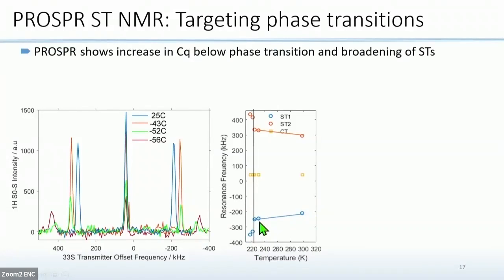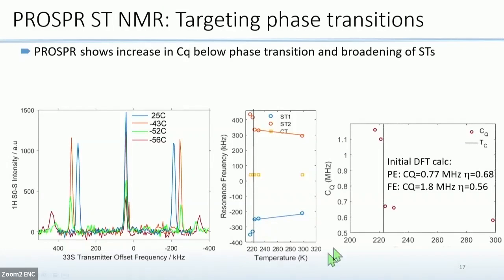And when we fitted all these spectra, we can see, PROSPR allowed us to see that there's a gradual change in CQ and then an abrupt change. And this agrees with some DFT calculations that we ran.